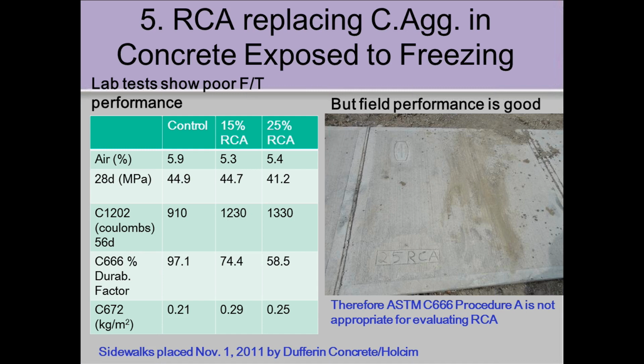In the field, we're not seeing that because, of course, the recycled aggregate acts like porous, lightweight aggregate that will release its water as internal curing for the concrete, and it won't be saturated unless you're pouring on November 1st or some days. But we did, and it didn't happen. So the concrete does dry out sufficiently that we're not getting that effect in real life. But if you only did laboratory tests, you'd say, well, this is no good.